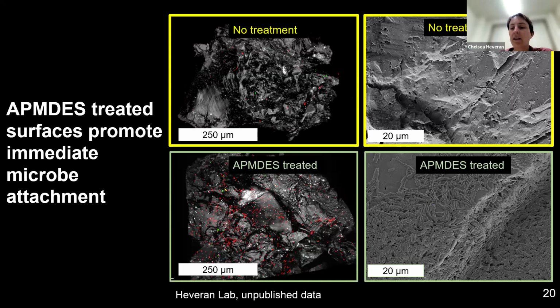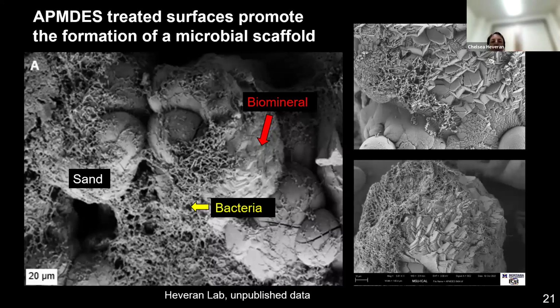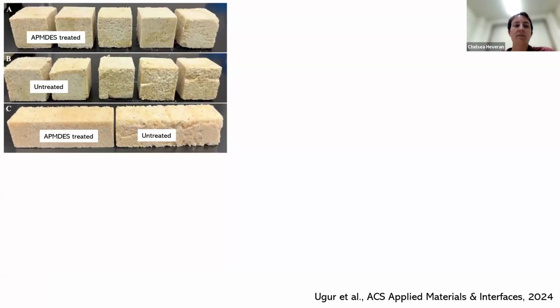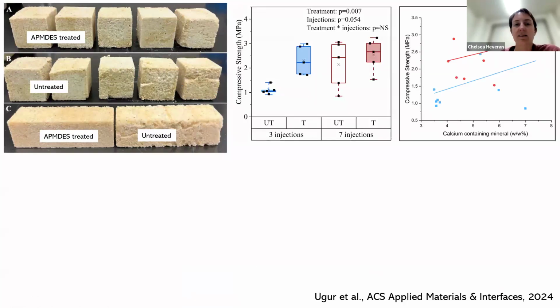They don't always survive, but they're stuck to the surface and their urease is available. We find that these microbes then create this really nice scaffold, and the scaffold of literally cells, we'll be talking about scaffolds later, helps promote this biomineralization of the structure. What this gets us is that when we have, let's say, untreated cubes and prisms, they're a little bit coarse, even after 7 injections. They have okay strength, but they're not very pretty. But with our treated conditions, we're able to build nicer things in the same amount of time.